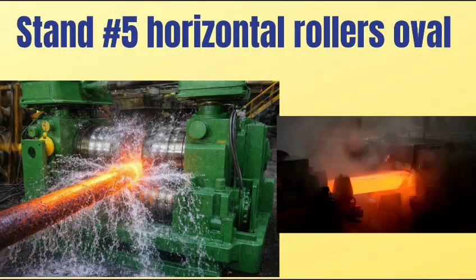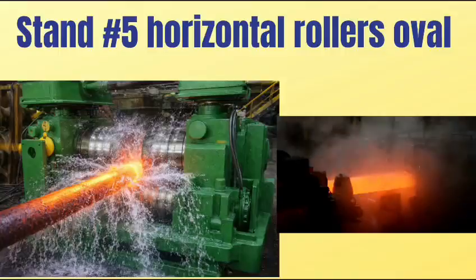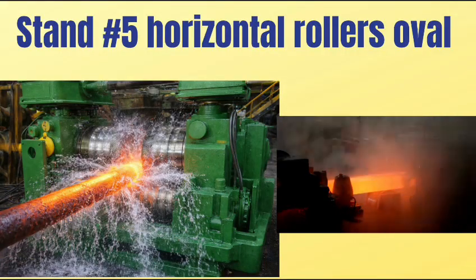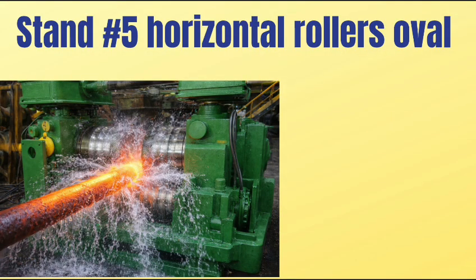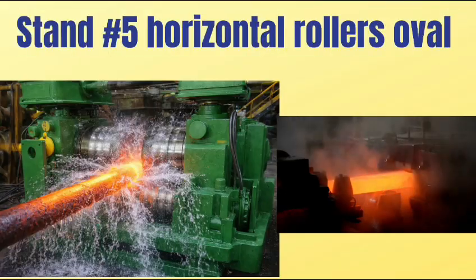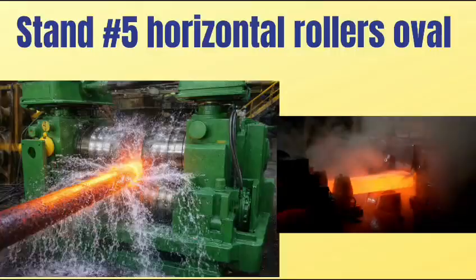Because of the rotation, the rollers grip and pull the billet in the forward direction. The billet reduction size is 65 mm to 52 mm. Reduction size is 13 mm. Force is applied by top and bottom. Oval to round shaping. Speed is 13 meters per second.